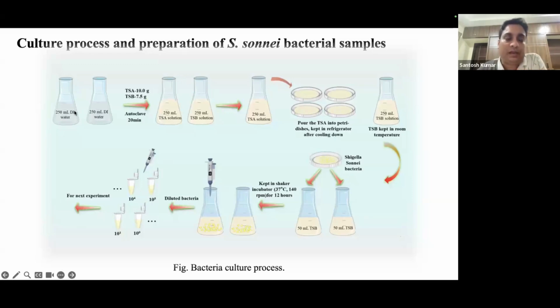So we need to take two 250 ml bottles of water, and then we need to use the agar media, and without agar media. Then we need to autoclave for 20 minutes, and then the agar solution we need to put into some petri dishes, and the one without agar media we need to keep at room temperature.